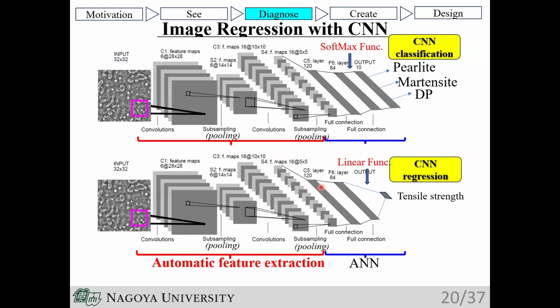In the fully connected layers of this regression model, convolutional features are extracted automatically from the input images. These features often reside in a high-dimensional space, sometimes exceeding 2,000 dimensions. Unlike traditional manual descriptors such as grain size and aspect ratio, these features represent abstract spatial correlations that are not intuitively interpretable by human researchers. Nevertheless, this black box nature allows the network to capture subtle, non-linear structural nuances in martensitic plates or laths that traditional geometrical analysis might overlook, enabling high precision prediction of materials performance directly from raw micrographs.